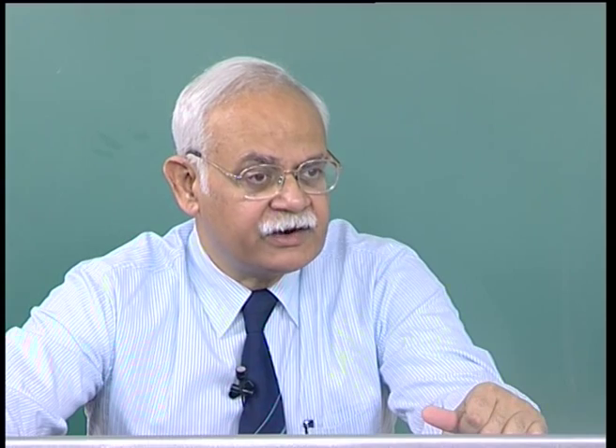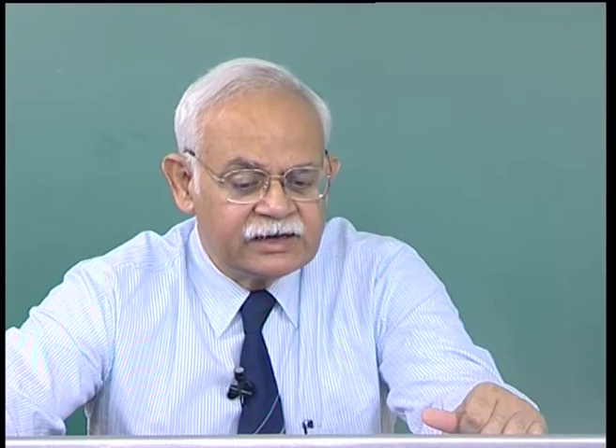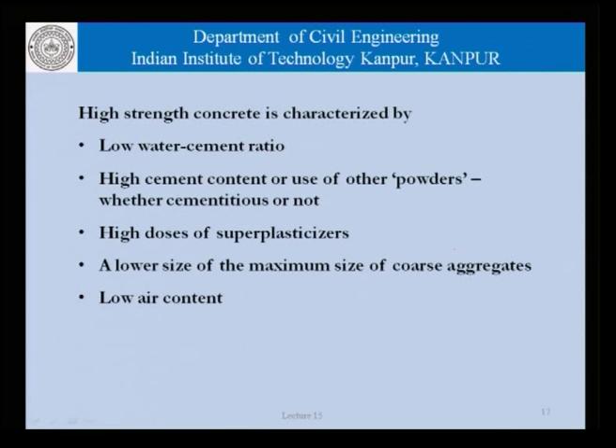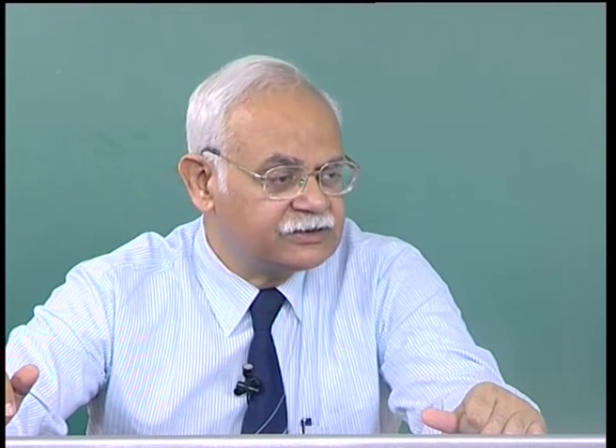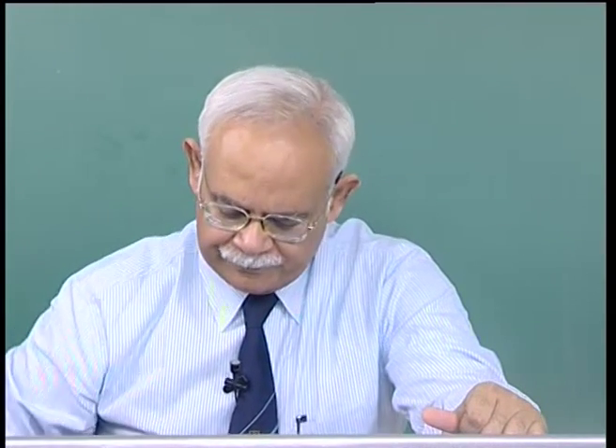That is why we try to reduce the maximum size of the coarse aggregate as far as high strength concrete is concerned. Once we reduce the size of the coarse aggregates, we increase the surface area, and once we increase the surface area, we need more mortar, more paste, and that is what relates to the use of mineral admixtures and other powders in high strength concretes. Low air content. High strength concrete is also characterized by a low air content. We shall see in a slide what are the provisions that are related to air content.